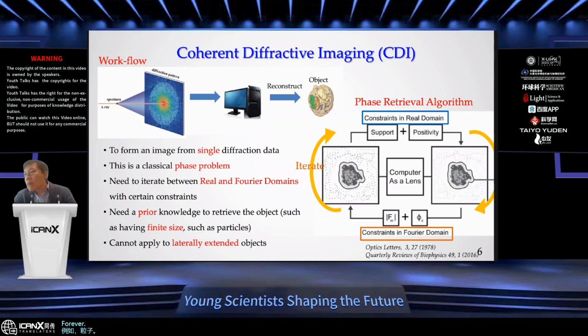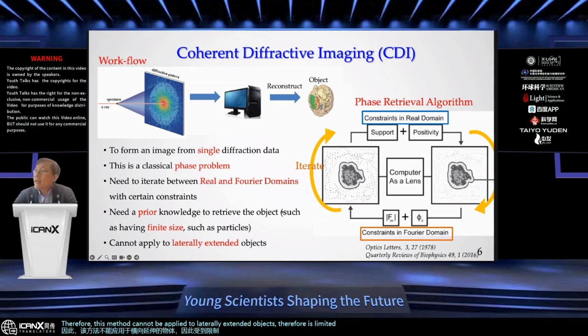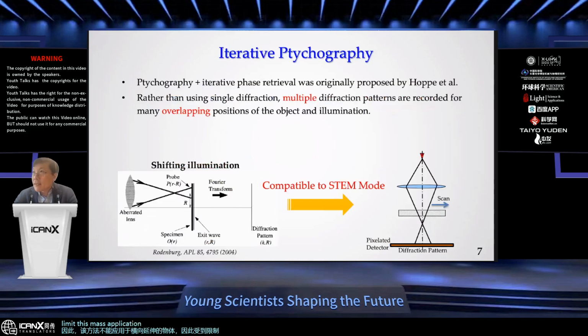However, because you have to have this prior knowledge, this method cannot be applied to laterally extended objects. Therefore, the application of this method is limited. Later on, there was a method called ptychography. Now people use ptychography plus this iterative phase retrieval method, which was originally proposed by Hoppe. And rather than take a single diffraction pattern, we now record multiple diffraction patterns with many overlapping positions of the probe and the sample.